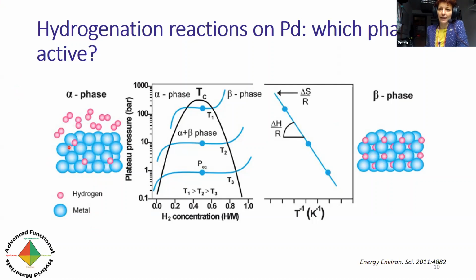And as long as the hydrogen concentration is low enough, that would not necessarily be an issue or a challenge or an opportunity, depending on the angle you're looking at. So it would form a kind of solid solution phase with palladium metal, whose properties would be essentially the same as that of the metal. Now, when we're increasing the hydrogen concentration or the hydrogen pressure at any given condition, what would happen is that at some point, the concentration of the hydrogen dispersed within the metallic phase would be high enough for it to penetrate and occupy the interstitial positions within the palladium lattice. And that is called the beta phase.